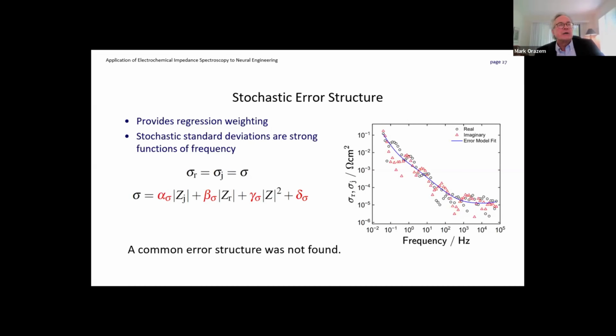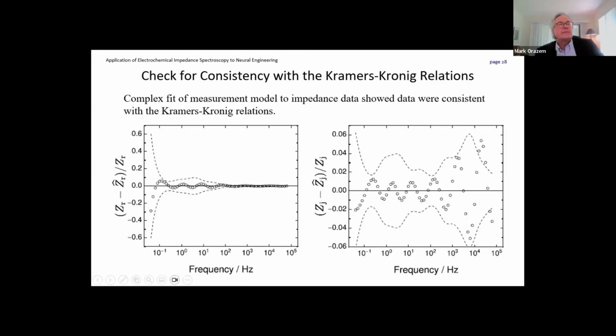Let me go back. Where am I? One other thing we could do is check for consistency with the Kramers-Kronig relations. In this particular case, we're using a complex fit of our measurement model to the impedance data. And you see that all these normalized residual errors fall within the 95% confidence interval for the fit. That is a way of saying that our data satisfy the Kramers-Kronig relations.